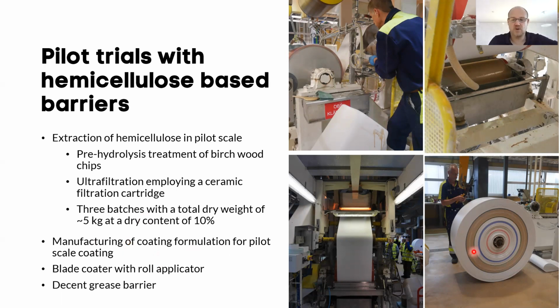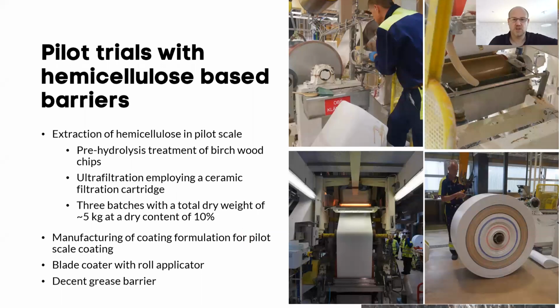And this is the result with the roll here. The brownish part here is the hemicellulose coated board. It's brown because you have a little bit of lignin within the hemicellulose coating too. We were able to coat this in pilot scale, and we had a decent grease barrier. So what we could show here was that we could do this. It was possible to do it in this way.